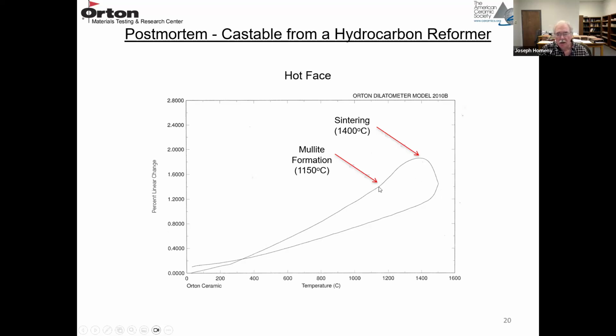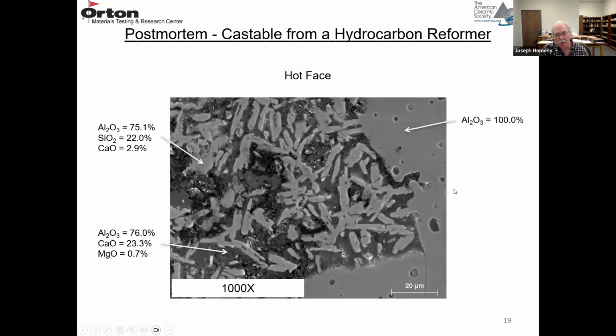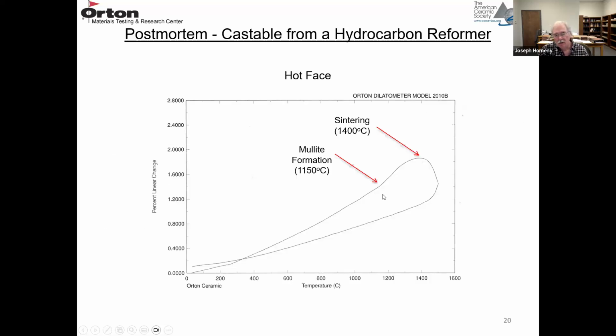So we know that this refractory right here that we extracted from the hot face did not see a temperature higher than 1150 degrees C, because if it did, that reaction would not show up as a slope change. So what this tells us is that the maximum temperature that the refractory saw in service at the hot face has to be less than this number, 1150 degrees C. That may be useful or it may not be useful, but at least we have an idea. It had to be below this temperature.